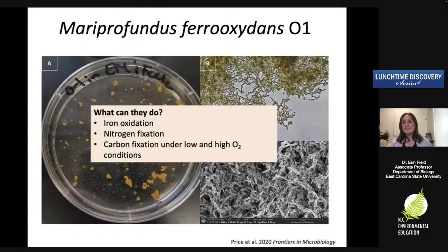Okay, so what did we find in the genome? We know it can oxidize iron. We confirmed that. That's great. But it can do more than that. Remember, they're not just going to contribute to corrosion or oxidation. They do other things in the environment. So we found that they fix nitrogen. That's a really important function in aquatic environments. Microbes, you know, really contribute to that. They fix carbon under both low and high oxygen conditions.